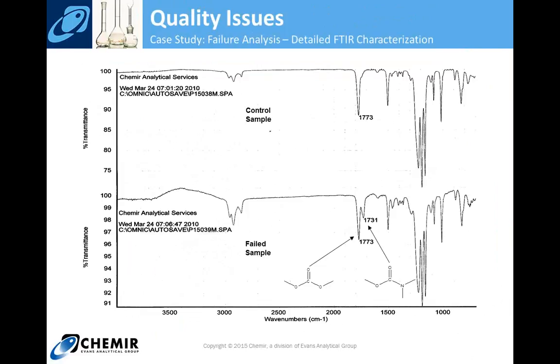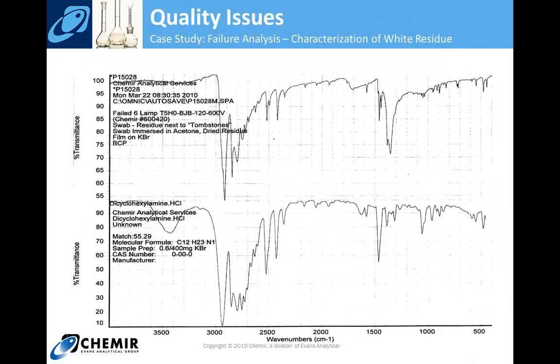Now, analyzing a failed material, one of those tombstones that actually cracked and failed, we looked at the polycarbonate. The top spectrum is the control sample of the polycarbonate. The bottom spectrum on this slide is the polymer resin from a failed sample, and you see some chemical differences in that failed sample. This is what we're looking for. We see some peaks in the IR spectrum that are consistent with a certain type of chemical functionality that should not be present with polycarbonate. So this is starting to give us some clues on something that's chemically attacking the polycarbonate.